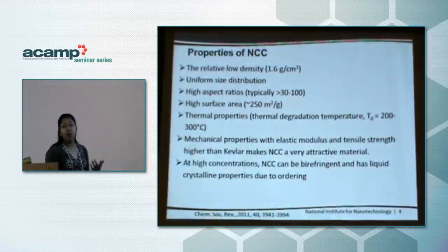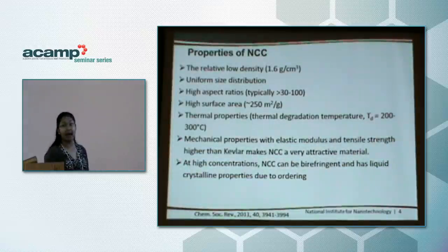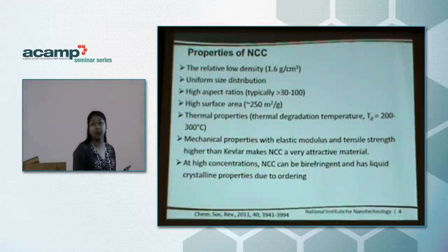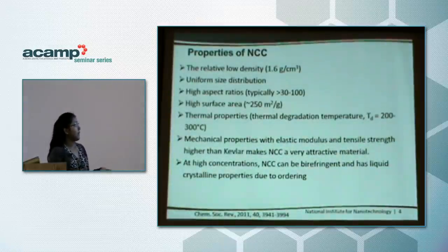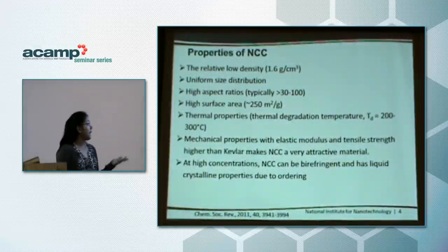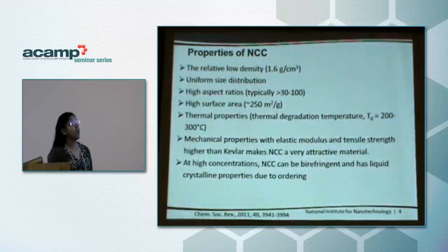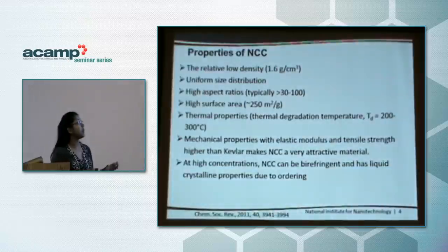Some of the properties of NCC are that it has a high aspect ratio, high surface area, and very good thermal properties — its thermal degradation temperature is fairly high. It is currently considered stronger than Kevlar, and at high concentration it has some liquid crystalline properties. It is also renewable and has fairly low cost.